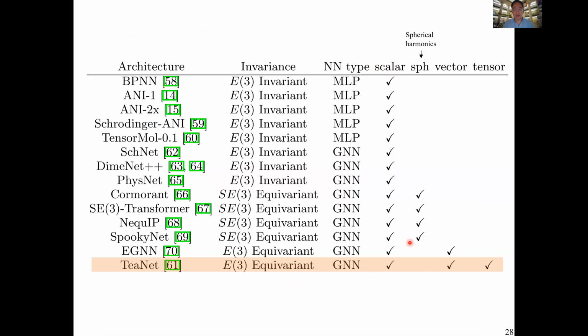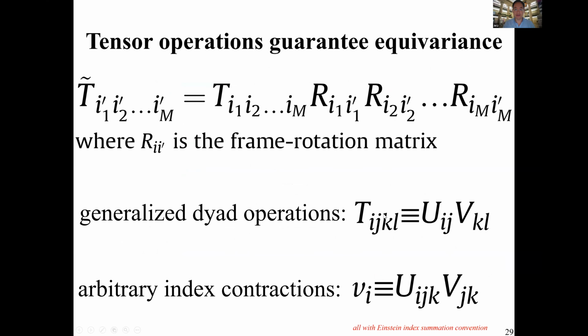But then there are also architectures such as Cormorant and NequIP, which use spherical harmonics. In our case, we use general tensors. In other words, rank 2 tensors, we could use also rank 3, rank 4 tensors, rank 1 tensor, which is a vector, as well as scalars. So we use, for the first time, all scalar, vector, and tensors, and we assign them to atoms as well as to bonds. And really, the tensor language was actually invented to guarantee equivariance.